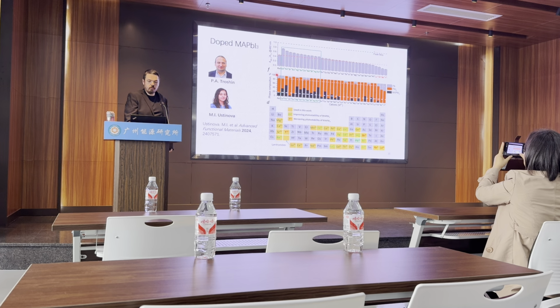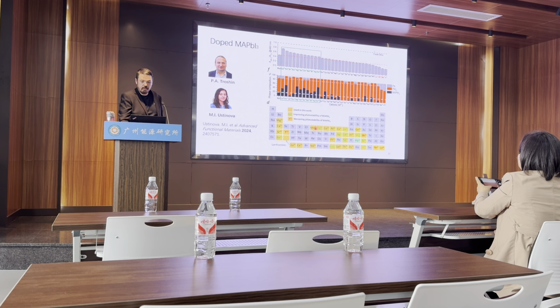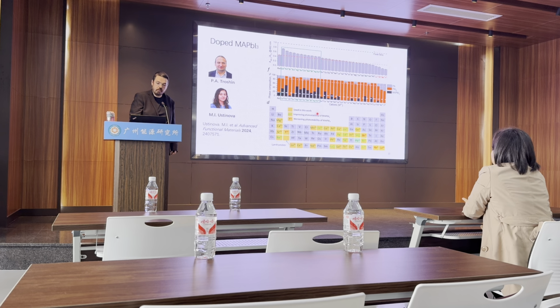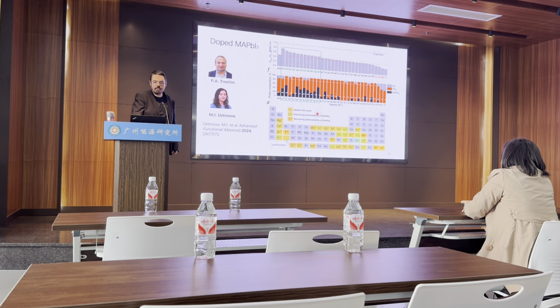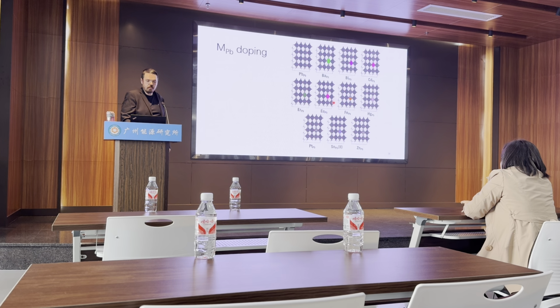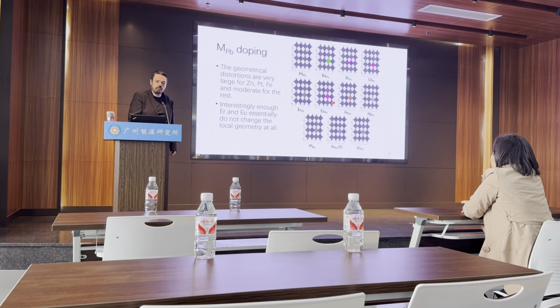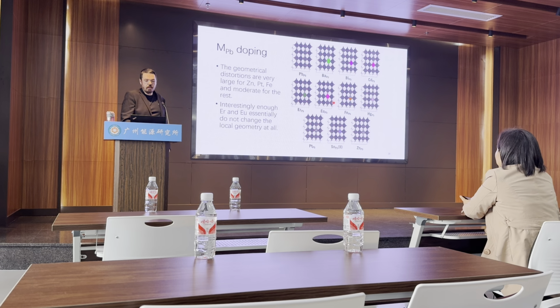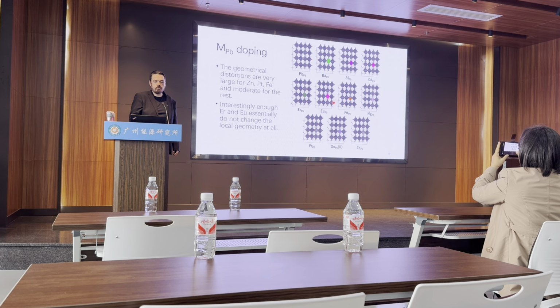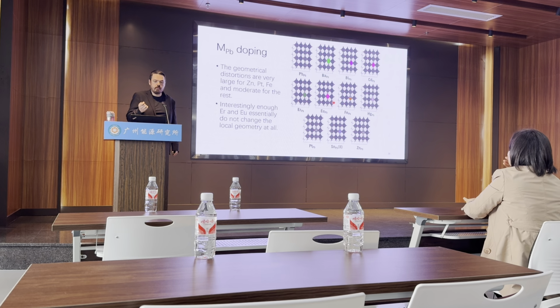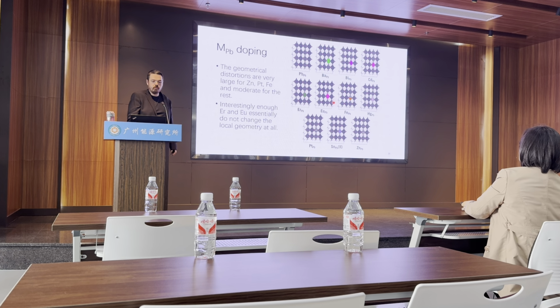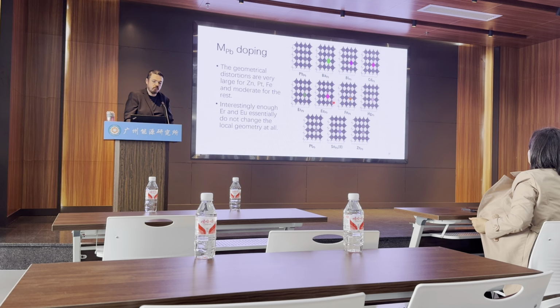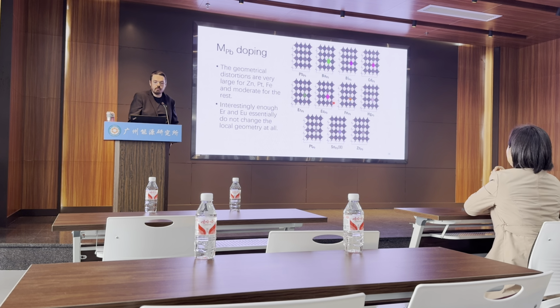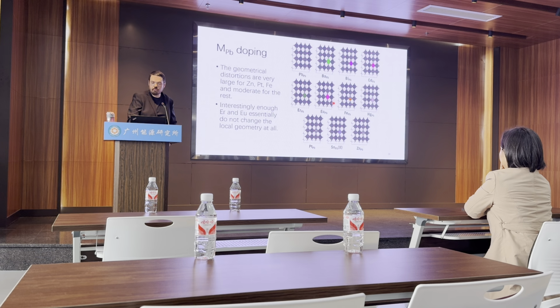She basically took half of the periodic table and doped it dilutely into perovskite. And then she analyzed the results. The main result I'll tell you in a moment, but I'll just say that we did a whole bunch of DFT as well. We found that the local geometry changes a lot with zinc, platinum, and iron. And for erbium and europium, it essentially doesn't change much at all, which is reasonable because they're big and lead is also large. So from a size perspective, it makes perfect sense.